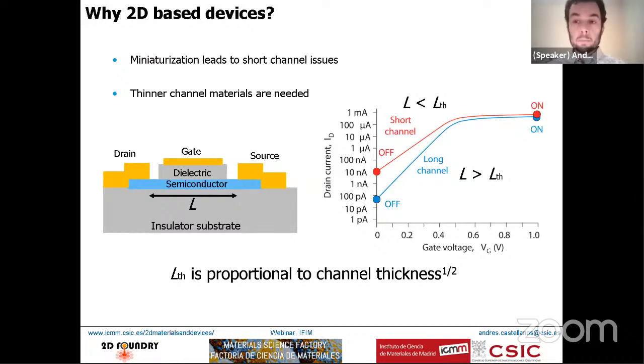So these defects in two-dimensional semiconductor materials typically shift the bands. For instance, in molybdenum disulfide, you have a naturally N-type semiconductor, because you have sulfur vacancies that dope the material with electrons, and also you get Fermi level pinning close to the conduction band - that is basically the effect we see in these materials with these defects.